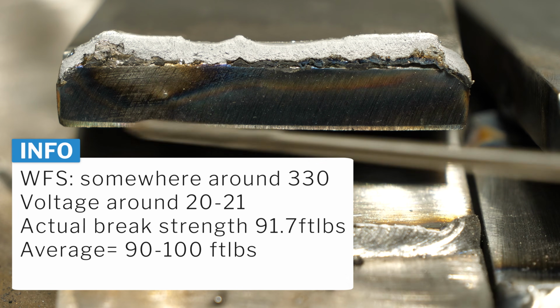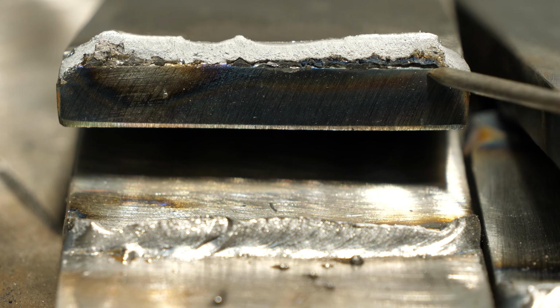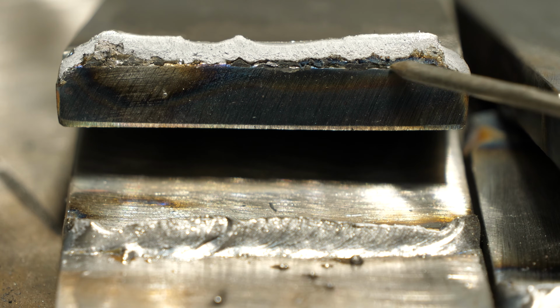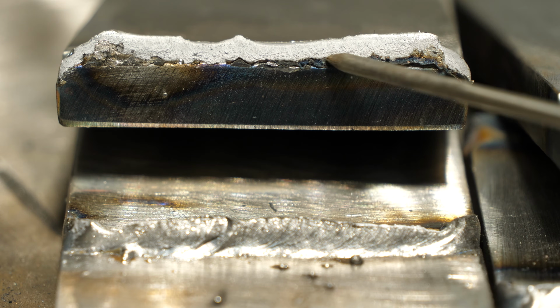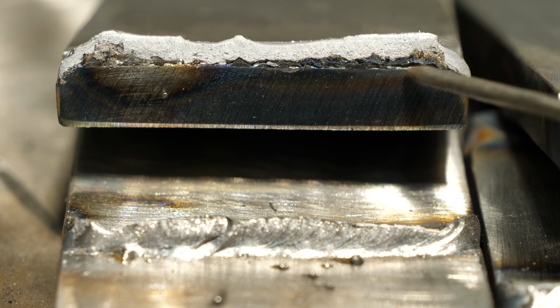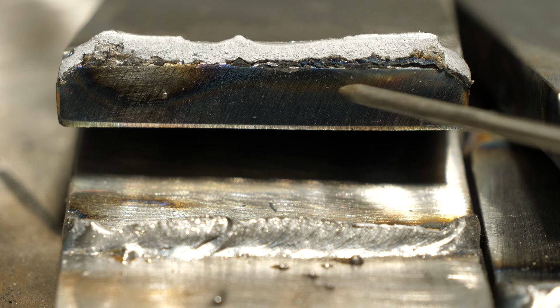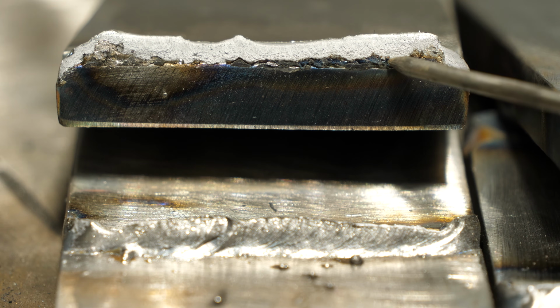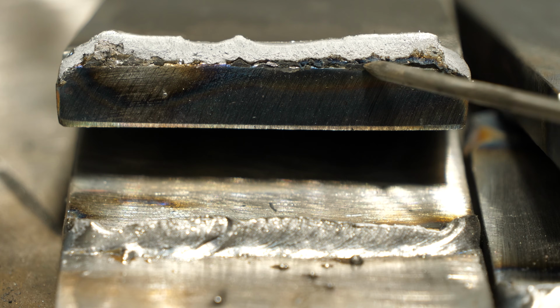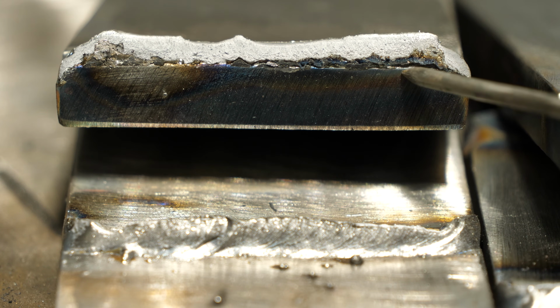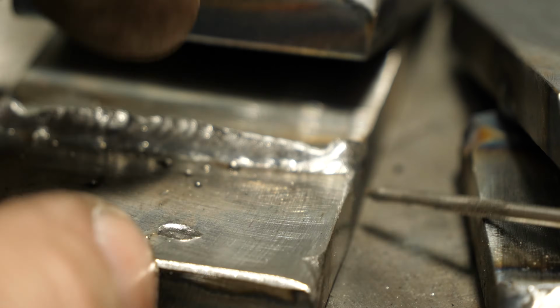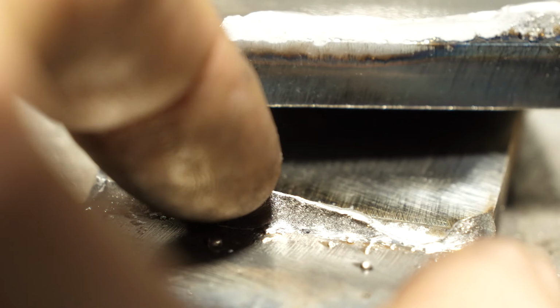So when you look at this guy, this is the one that was sputtering due to poor drive roll tension. This whole upper edge here that's visible pretty much all the way down, that's all original plate edge. So this has zero root fusion and has no penetration. If you look where it broke, like this black line here, the weld basically just broke on itself there. It wasn't actually fused to this at all. So this had the lowest numbers. They weren't terrible for the sake of this break test. However, they were lower than the other ones, and it really goes to show, if you know something isn't going right, fix it, and be smarter to gouge this out and repair it. So that's not good.